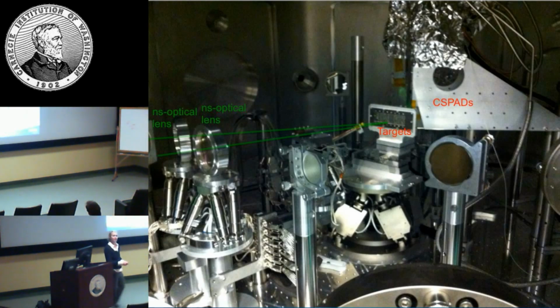Okay, so what do we see here? This is an ambient condition fused silica pattern. So we should see no diffraction here. It's a glassy SiO2 material. Maybe we have some diffuse signal here. 2 theta increases left to right. This is a 0 time delay, so we should really see nothing. There's some blemishes from damage on the CSPADs downstream.